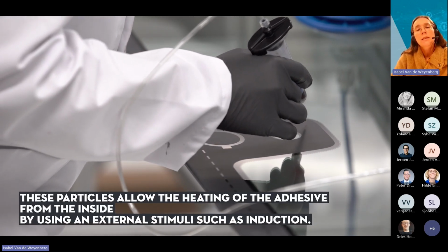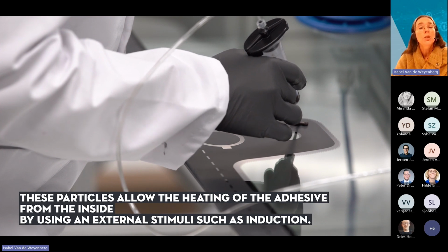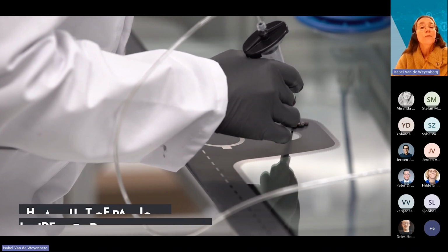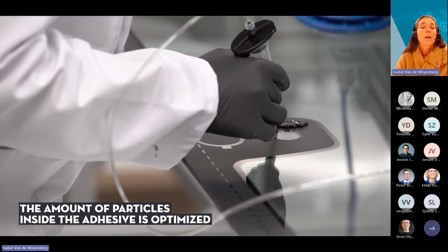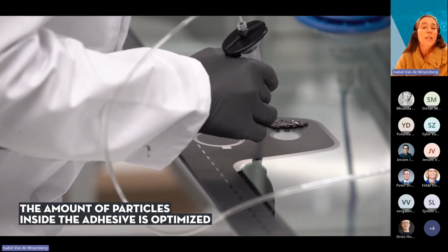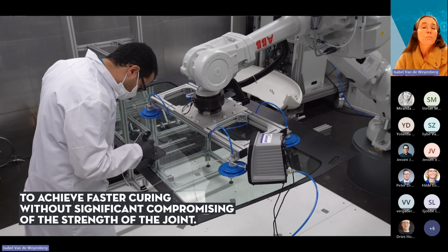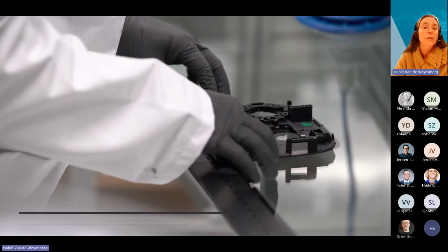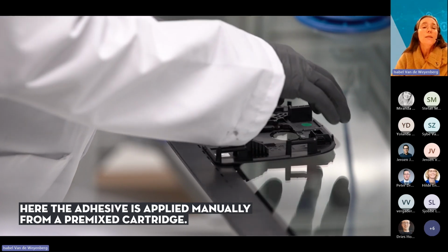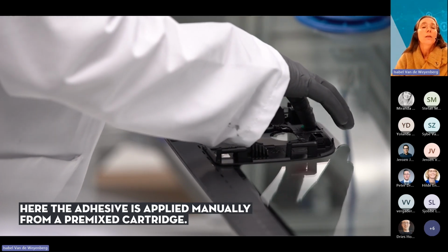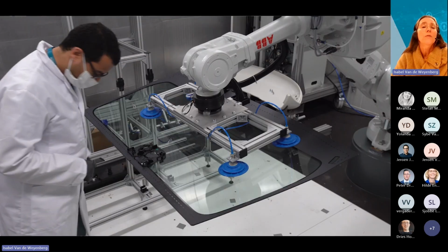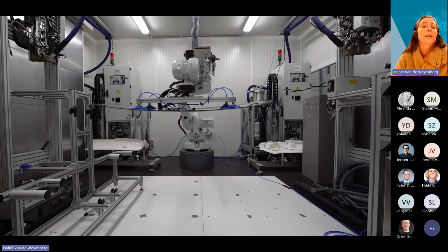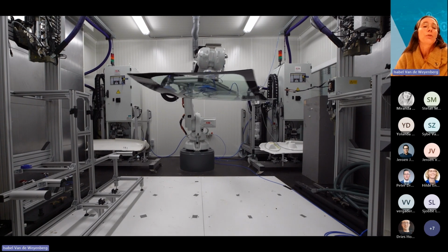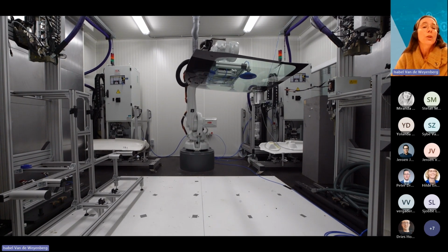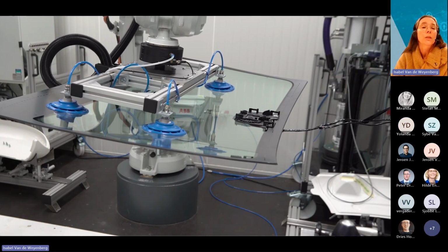And a nice thing of this example is that in real life, these windshields are quite often cured for several hours in a separate stock location. So you need to have enough surface to stock your windshields during production. With this technology, you will see that just within a couple of minutes, you can secure already your sensor. You can bond your sensor to your windshield and your production process will not be interrupted.